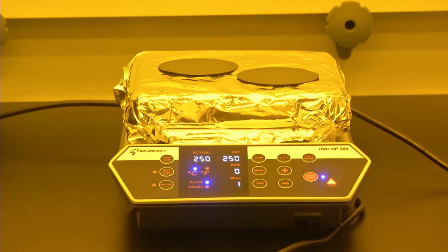So now 2 hours have elapsed since we kept it for the second stage of curing, and therefore the wafers can be taken off from the hot plate, and my colleague will do the procedure.